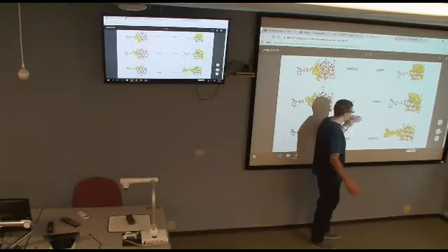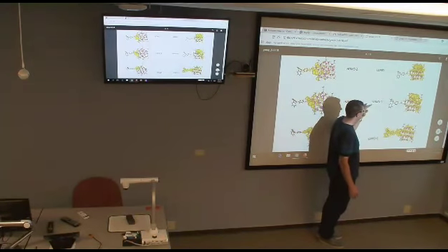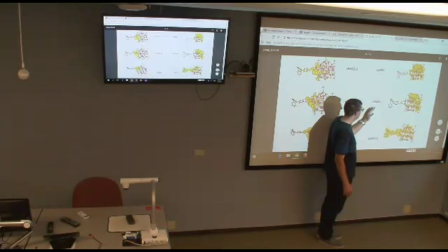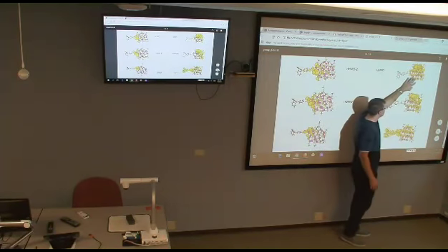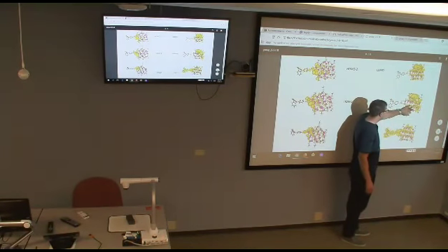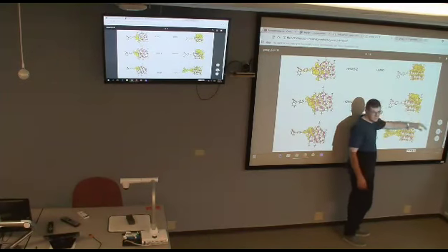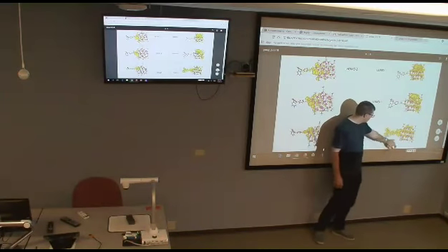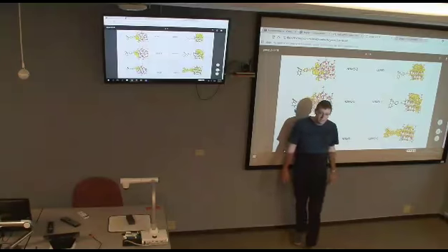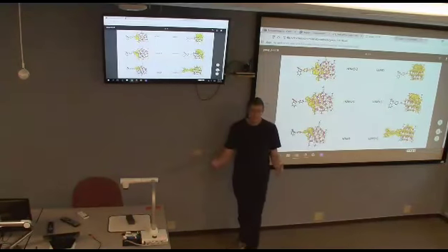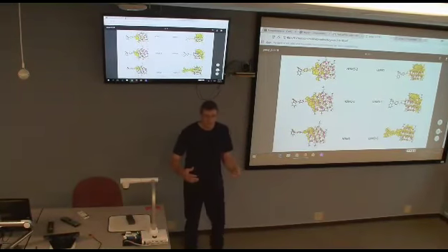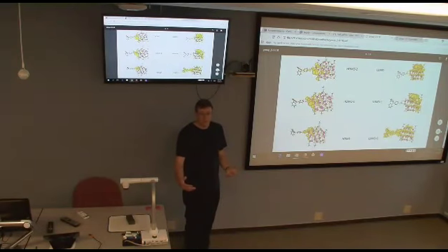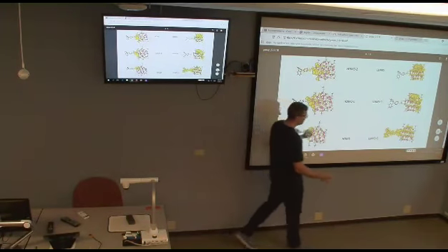One of the things that was a little concerning in going up into the conduction band was that it was still localized primarily on the quantum dot itself for the first few states, but then you get a few random states that look like this, where now you have partial charge density delocalized on a large portion of the organic linker and the organic piece itself.